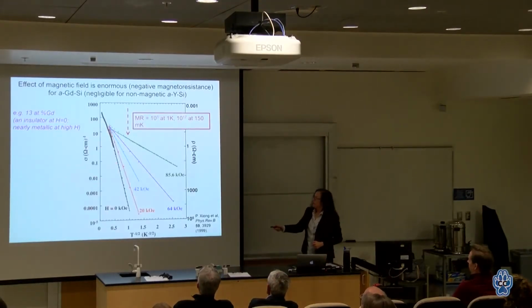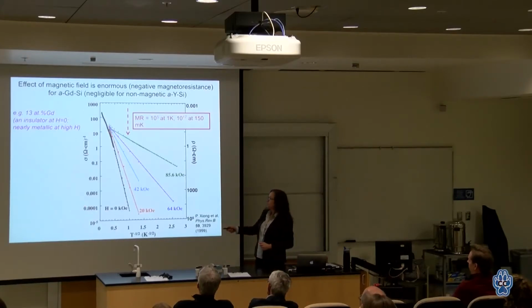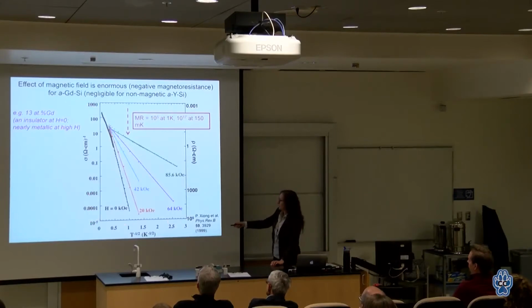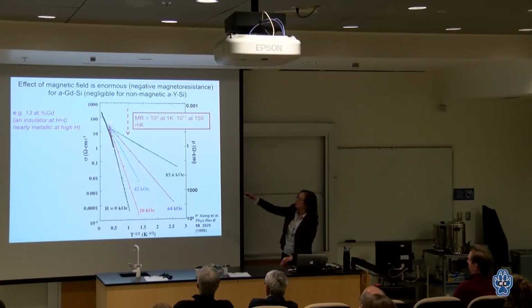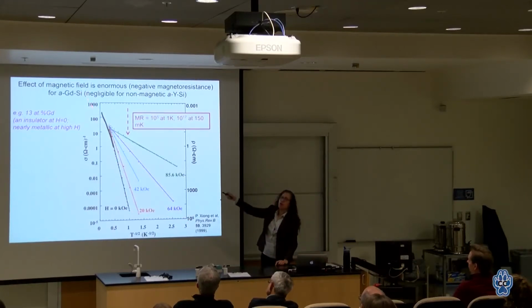This is a plot. This is now the conductivity of gadolinium-doped silicon, at 13%, on a log scale as a function of temperature. It's inverse temperature, so there's room temperature up here on the left. This is low temperature here on the right. At zero field, this is strongly, strongly insulating. As I apply a magnetic field, it becomes more and more metallic. This hasn't gone all the way through. Fully metallic would be flat. But it is heading up towards being a metal.